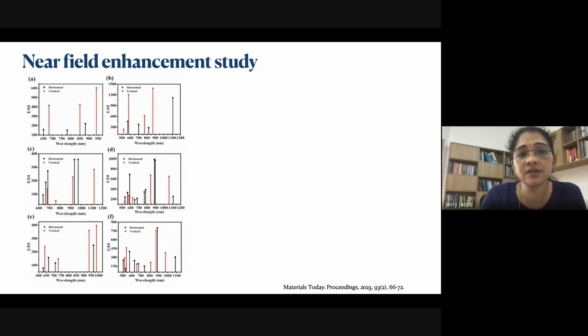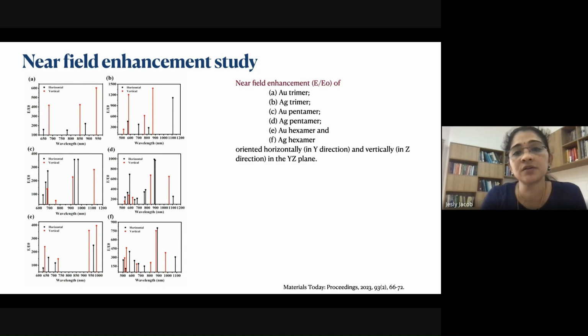Now let's see the near field enhancement study of these structures, where we have analyzed more arrays of these structures. The first one is that of a gold trimer, and the second one a silver trimer. The third one is the gold pentamer, and the fourth one the silver pentamer. The fifth one is a gold hexamer, and the sixth one the silver hexamer. And also we have changed the orientation, that is, the whole structure is oriented horizontally first, in the y direction in the YZ plane, and we have taken the field enhancement study, and also it is moved vertically in the Z direction and we have taken the enhancement study.